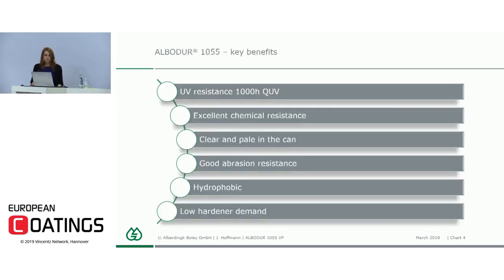So the goals we wanted to achieve: we wanted to have a 100% VOC-free resin, which survives 1,000 hours QUV. We tested here QUV-A as well as QUV-B. Additional to that, we wanted to keep high chemical resistance. And of course, we wanted to have that pale, clear, and whitish appearance. Compared to standard polyols, we have the same kind of abrasion resistance. And of course, because it's still a castor oil, we have a very, very high hydrophobic character.